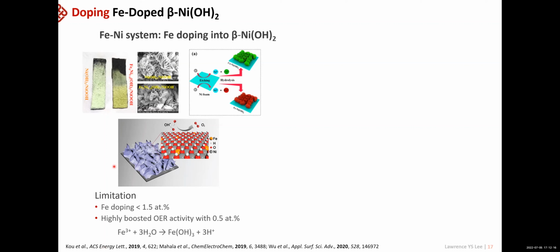One of the examples of using iron doping to enhance the OER activity of nickel hydroxide species was done by Kou et al. They tried to grow nickel hydroxide directly on the nickel substrate by a wet chemical method, which is probably different from Professor Hu's previous work. And then they tried to dope, and they only managed to dope up to a maximum of 1.5 atomic percent. So it was quite difficult to go over this.